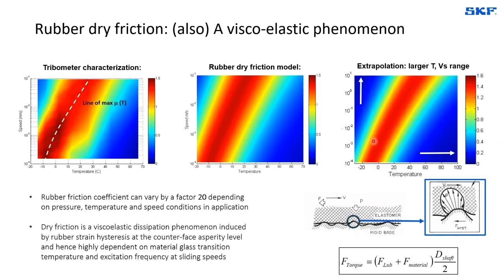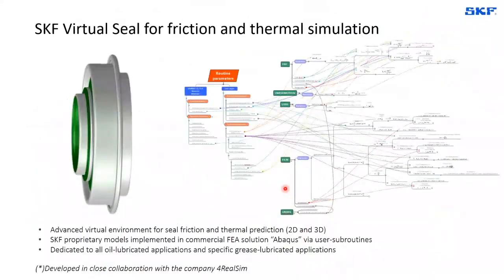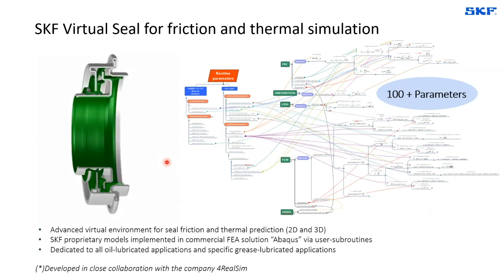Once this dry rubber friction is understood, then combined with the visco shearing of the oil, the lubricant in place in the contact, we are then able to predict the torque for the seal, leading ultimately to frictional heat and then potentially to heat conduction and heat convection in the system, which we are able to capture. In order to do that, we have developed an even more advanced version of our SKF virtual seal, in addition to what I was showing for the transient dynamics before, where we are able, via the combination of more than 100 parameters, to predict the seal friction, but also the frictional thermal heat generated under the lip, for example, and then conducting and finally dissipating through the seal, and in some cases, if need be, all the way through the system.